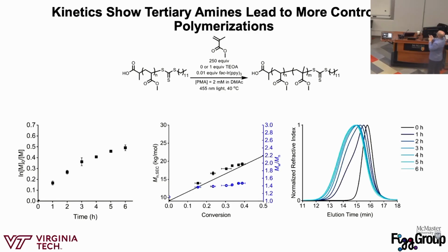And if we look at the size exclusion chromatograms, we see them shifting to lower elution times, and this peak is going down over time. So all of this data is showing us that under the right conditions, which I'm glossing over, but I'll talk about in a minute, we can actually get relatively controlled polymerizations. Are they perfect and beautiful? No. But again, this is the first time that you've been able to do this with RAFT polymerization that has been around since 1998. Well, earlier than that, but it was named RAFT polymerization in 1998. So we're really excited about this.